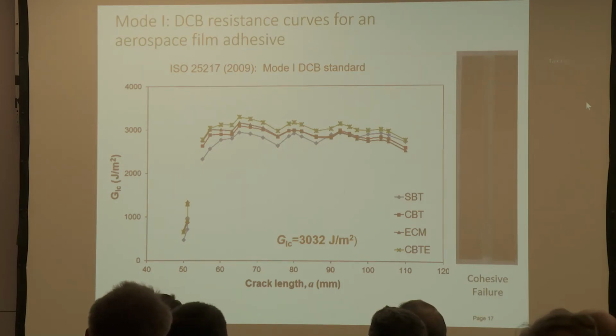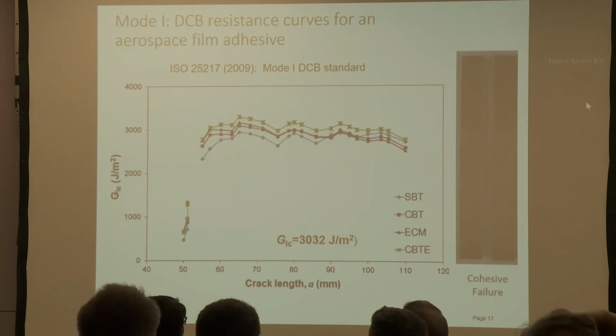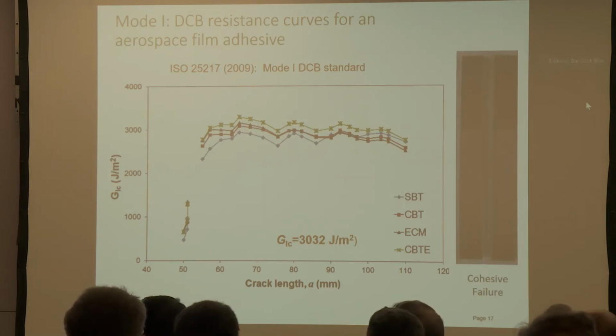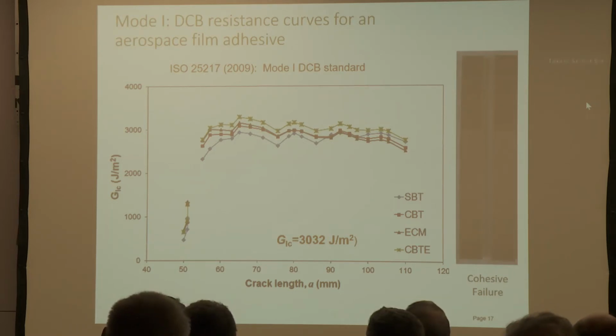But this is a fracture test specimen. You can see the adhesive on the right, and this is a structural film adhesive. So this is the sort of adhesive that may well have been used in an aircraft application. And you can see that we generate an R curve. The methods are in broad agreement in this case, and you can see that we've got a fully cohesive fracture surface. So there are no aspects of interfacial failure in what we're looking at.